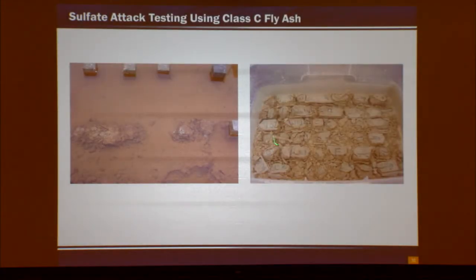Here's some research we did. This is actually some of my research from when I was in grad school. This was probably a month into the test. Completely disintegrated. This had a high calcium C ash in the mix. The F ashes went 18 months. Here are some exposure blocks or prisms that were in a tank, and they completely disintegrated.